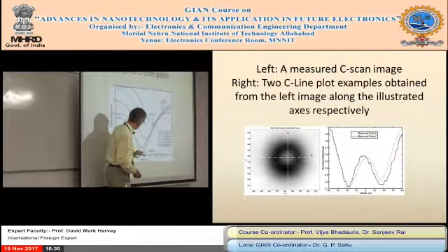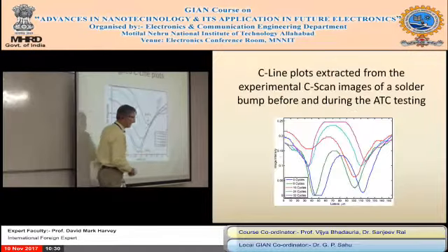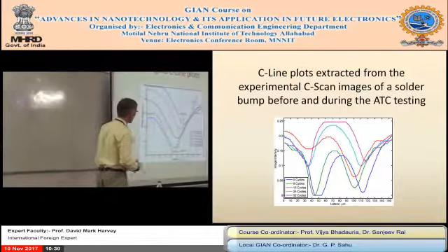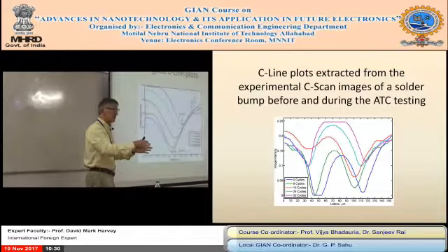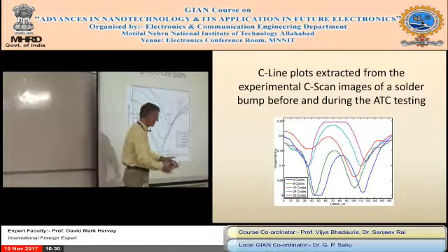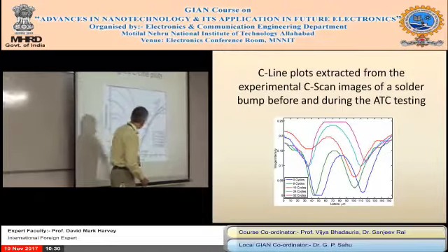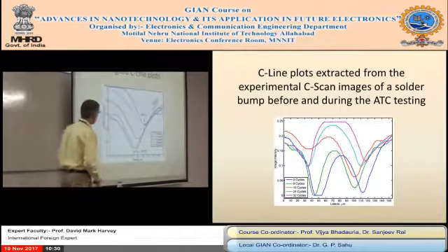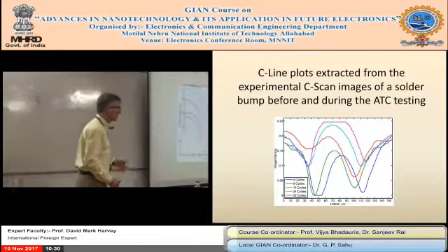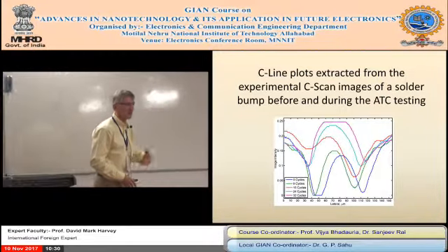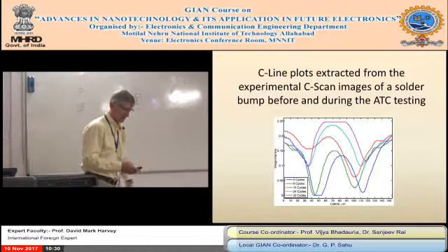Well, you could say it's the values starting down there, each cycle is creeping up. At the same time, this gap is growing. The bright spot is growing. This is the donut around the bright spot creeping up. And after 32 cycles, the joint's either broken, in most cases, or on the way to cracking.